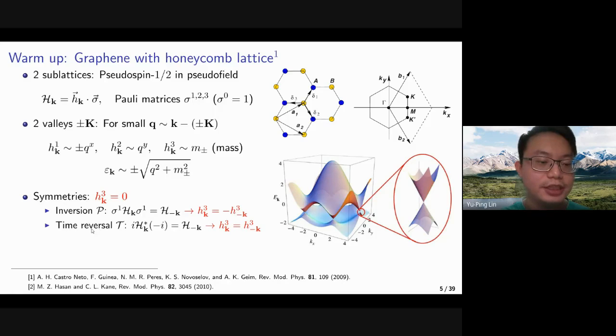Meanwhile, there is also a time reversal symmetry, which corresponds to the complex conjugate of the Hamiltonian. And because the momentum is also reversed, that is, k is mapped to negative k under time reversal, we're also relating the Hamiltonian at K and minus K. And under time reversal, the third component should be equal for K and minus K. So by combining both inversion and time reversal, we find that the third component at K should be both negative and positive, equal to the third component at negative K. So it requires that the third component should vanish.